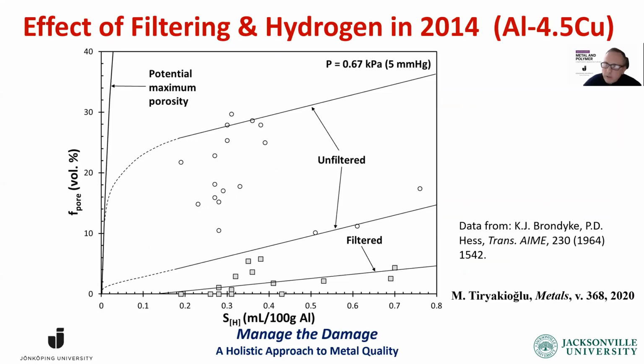And then this is this wonderful study from 1964 from Alcoa. They worked with an aluminum 4.5% copper alloy, 2014. They had two different levels of vacuum. I'm looking at the lowest vacuum. This is very, very low, about 0.6% of 1 atmosphere. And they looked at the effect of filtering, deep bed filtering. And obviously, when you filter, you get much less pore volume, and that makes sense.